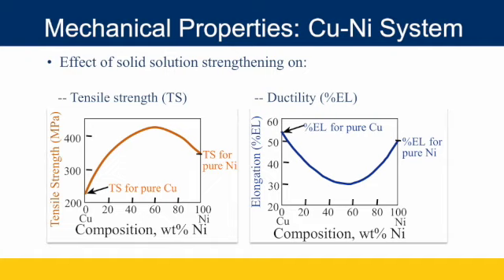So if you read this graph, we have 100% copper or 0% nickel, 100% nickel, 0% copper. This is the tensile strength of the pure materials. Obviously, copper is very weak compared to nickel. It only has a tensile strength of about 220 megapascals, whereas nickel has a tensile strength of about 370. Okay, so I'm reading that off of here.